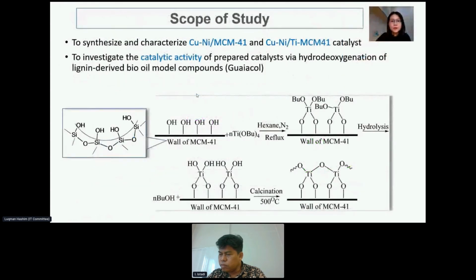This is the scope of the study, where our focus is on preparing the copper-nickel bimetallic catalyst supported by titanium-doped MCM-41. We also focus on investigating the catalytic activity of the hydrodeoxygenation process using the bio-oil lignin compound, guaiacol. As the mesoporous silica MCM-41 is mildly acidic in nature, modifications are made to improve the properties of this catalyst support by incorporating titanium metal salts through the hydrothermal process. This helps to improve both the Lewis and Bronsted acid sites of the catalyst, and also improves the redox sites of the catalyst.